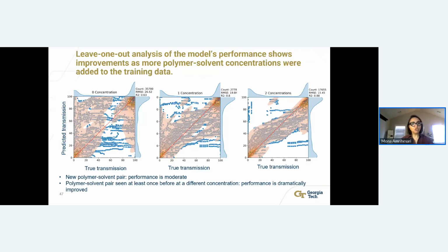And then for making sure that this is accurate for even unseen polymer and solvent cases, we did the leave-one-out analysis for the model performance, meaning that we tested the polymer and solvent cases where the model does not have that in its repository, or it's not trained on this specific polymer and solvent system.